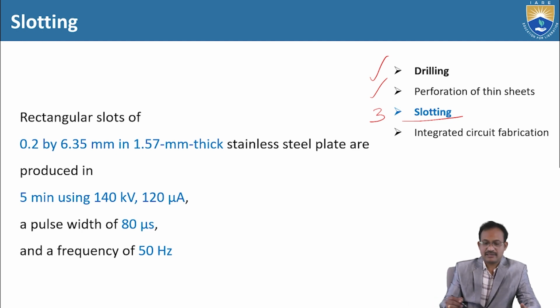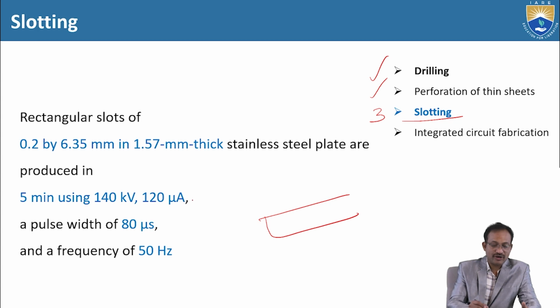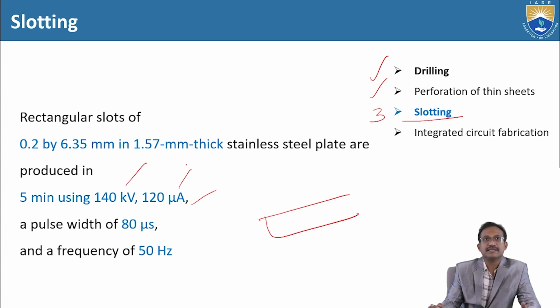Rectangular slots of 0.2 by 6.35 mm in 1.57 mm thick stainless steel plates are produced in 5 minutes using 140 kV, 120 microampere. So this is voltage, this is current, this is time. And a pulse width of 80 microseconds and a frequency of 50 Hz.